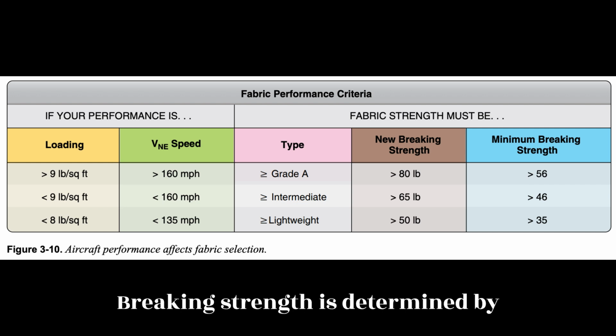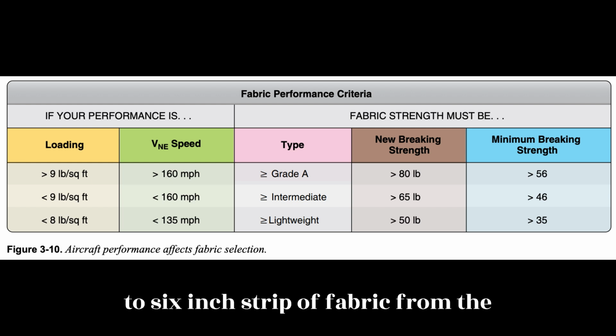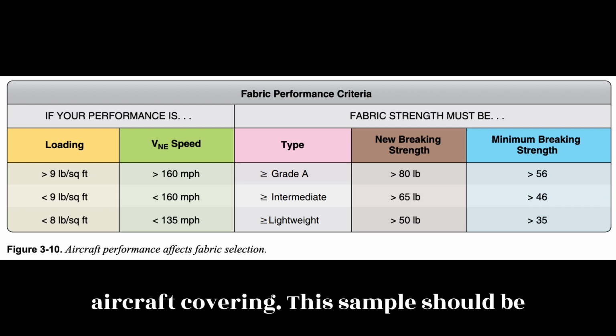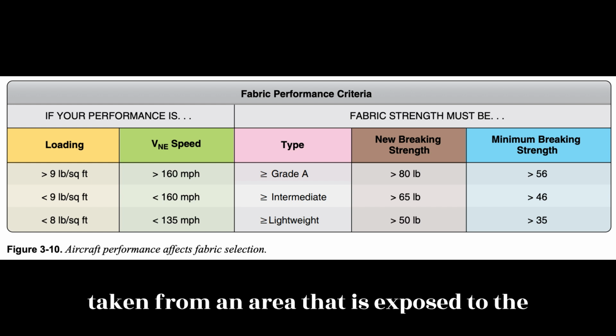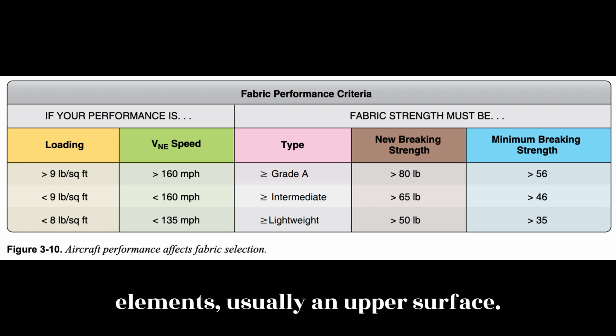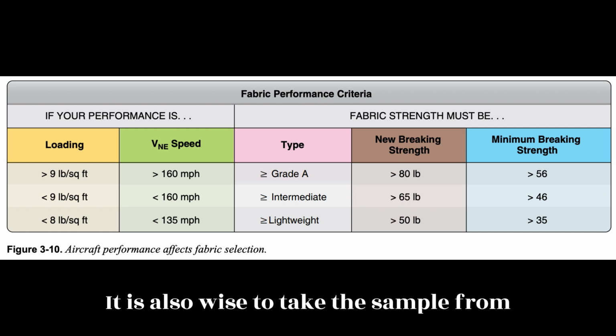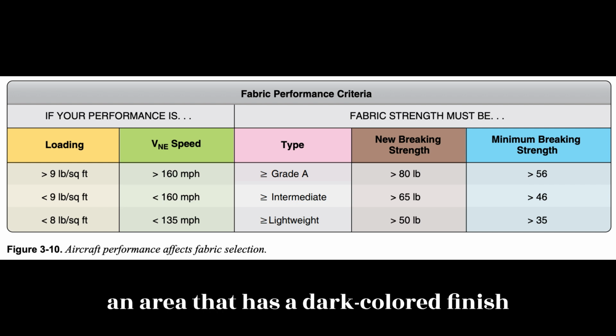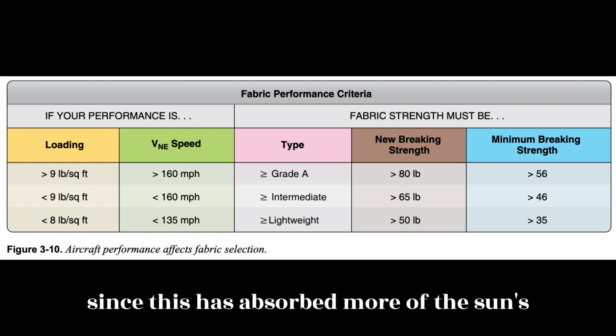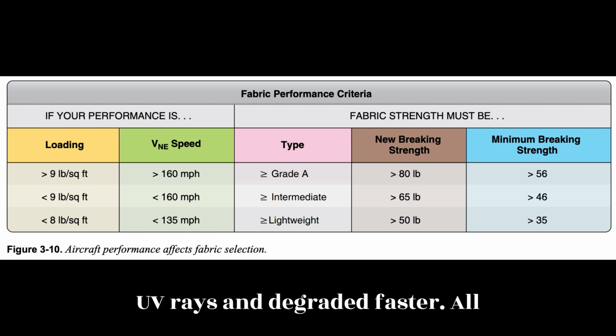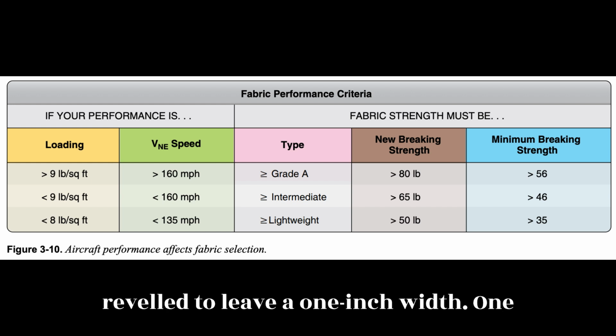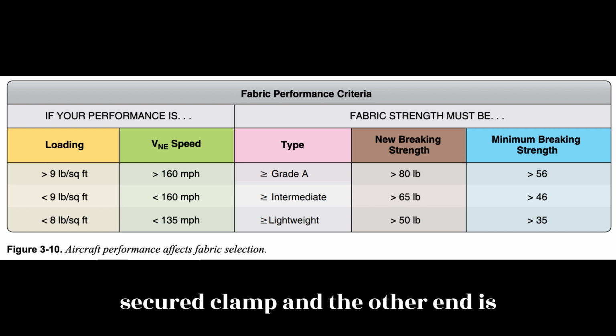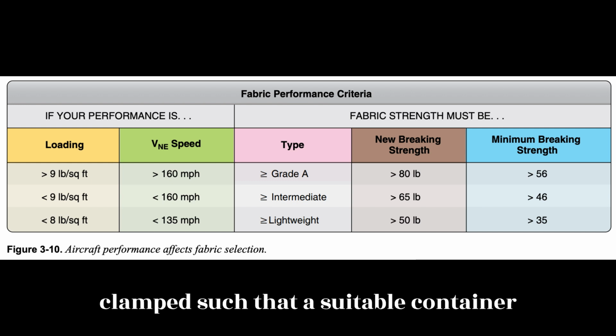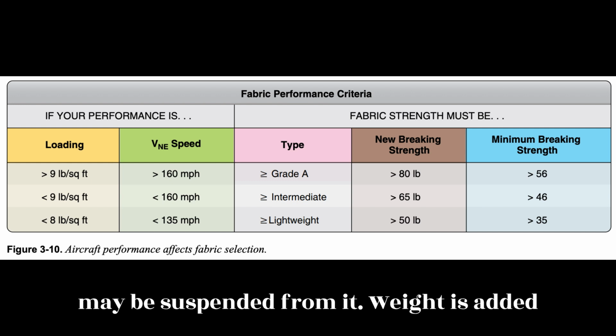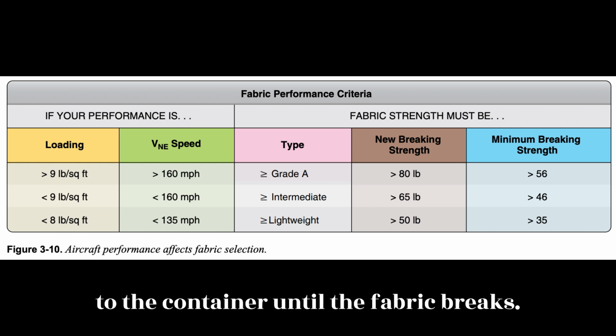Breaking strength is determined by cutting a 1 1/4 inch by 4 to 6 inch strip of fabric from the aircraft covering. This sample should be taken from an area that is exposed to the elements, usually an upper surface. It is also wise to take the sample from an area that has a dark-colored finish since this has absorbed more of the sun's UV rays and degraded faster. All coatings are then removed and the edges reveled to leave a 1-inch width. One end of the strip is clamped into a secured clamp and the other end is clamped such that a suitable container may be suspended from it. Weight is added to the container until the fabric breaks.